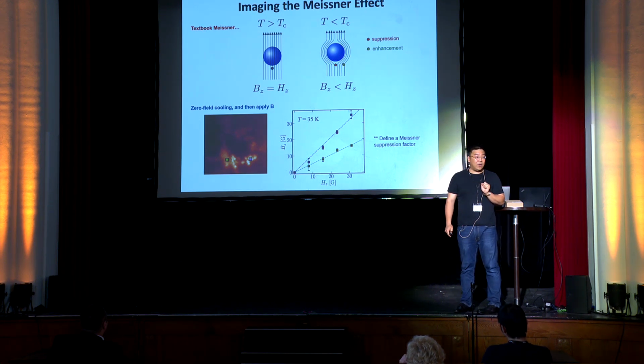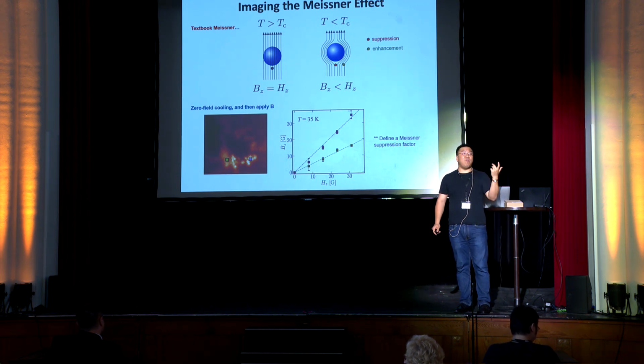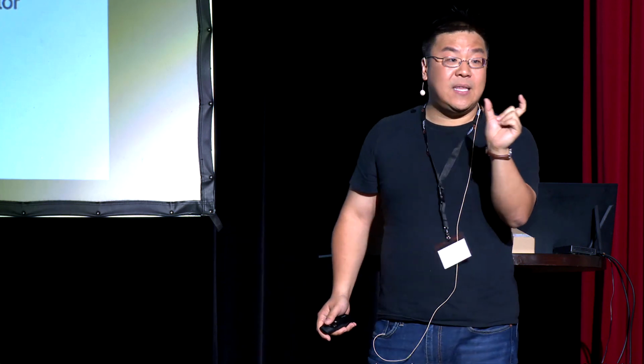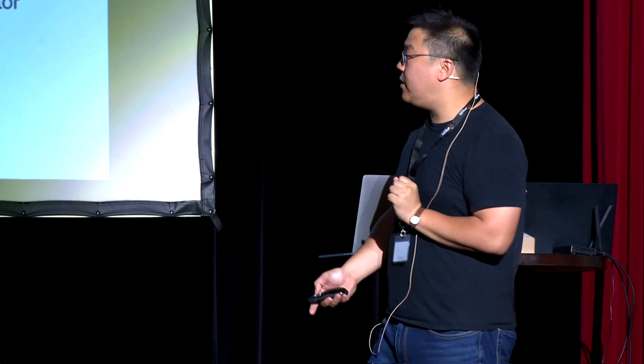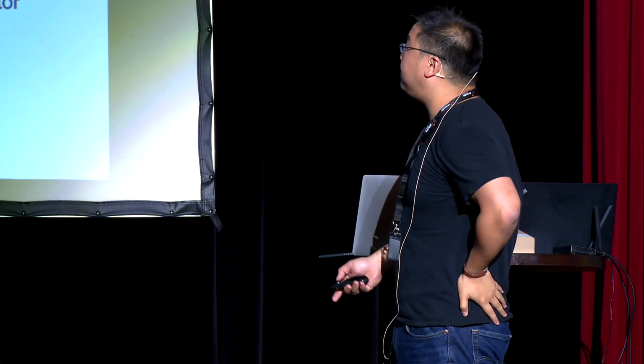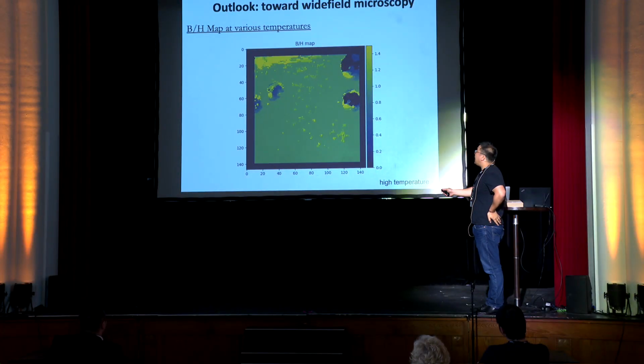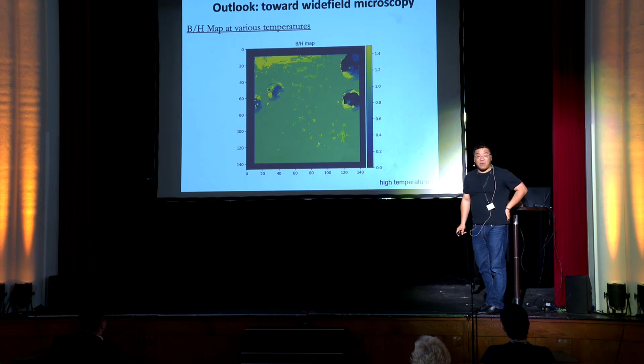So perhaps from a magnetism perspective, the simplest figure of merit that one can imagine is just defining a suppression factor. So relative to the slope being 1, what is the slope of the magnetic field measured by the NV relative to the magnetic field applied on the sample? Okay? So that'll be some number that could be greater than 1 if there's enhancement, or less than 1 if there's suppression. So here's exactly this type of measurement, but now shown in a wide field microscopy image.